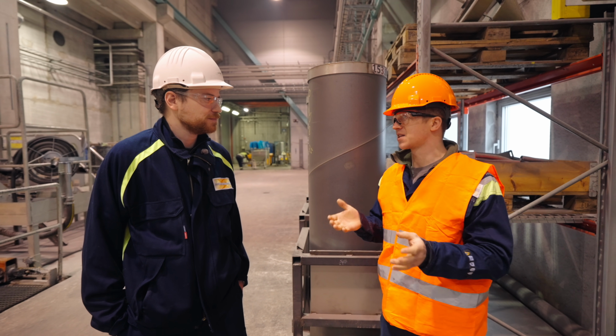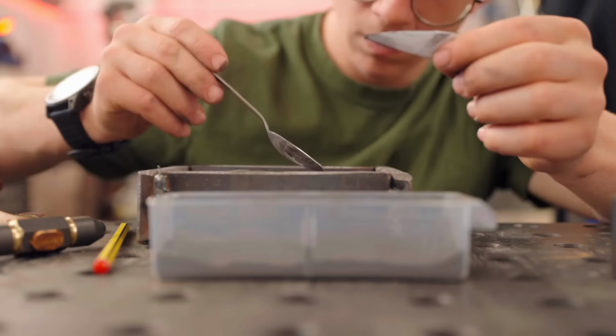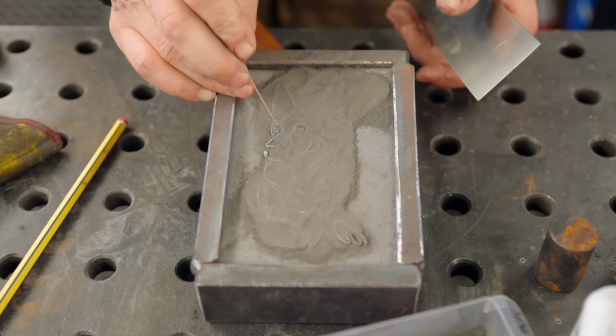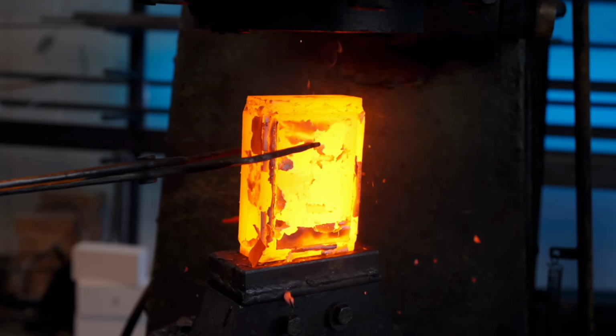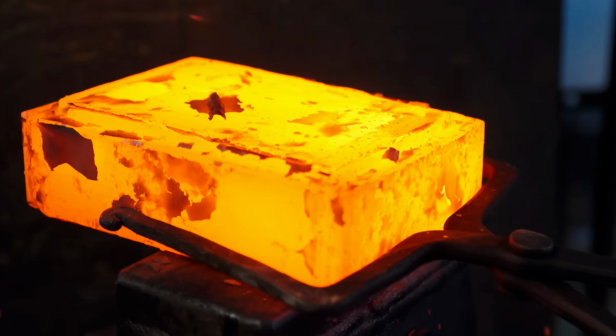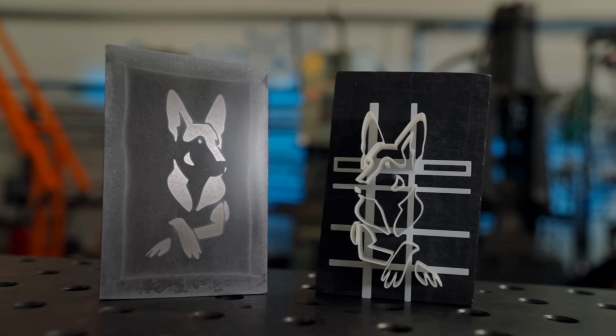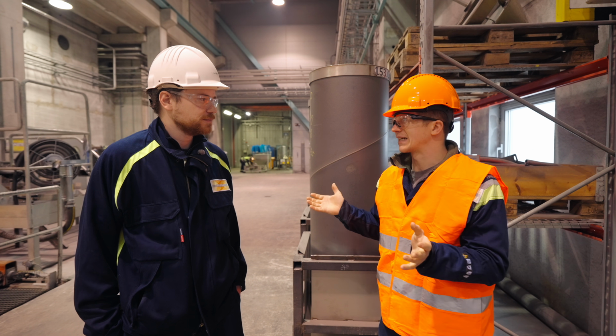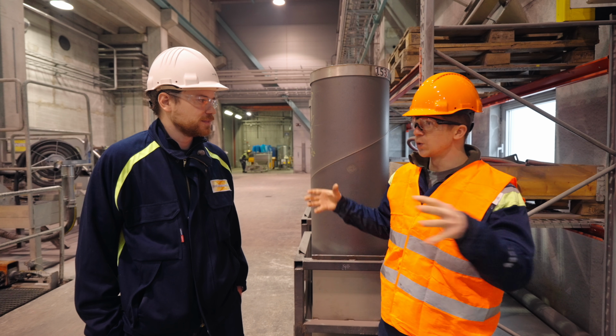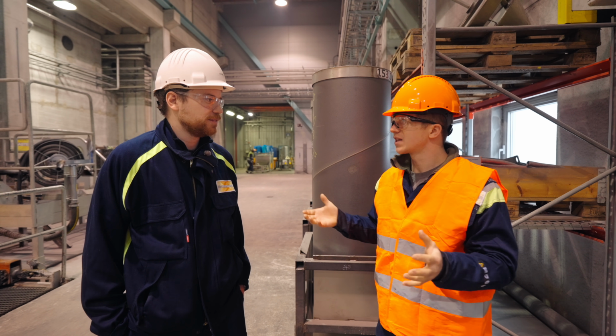Because even when I make canister Damascus out of powder, I actually need like 10 millimeter wall steel for it to compact nicely and not make big voids where the powder then blows out. You don't have those problems with hot isostatic pressing because the pressure comes from all sides evenly. Correct. Thanks to that high pressure gas.